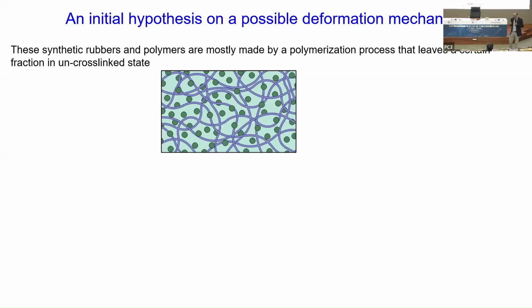The way you make silicone rubber is you basically take a polymer base and you add a catalyst into it. And that's how you start off a cross-linking reaction, and then you get yourself a rubber. Now, it is perfectly conceivable that that cross-linking was not complete, that you did not complete the cross-linking when you added that catalyst.